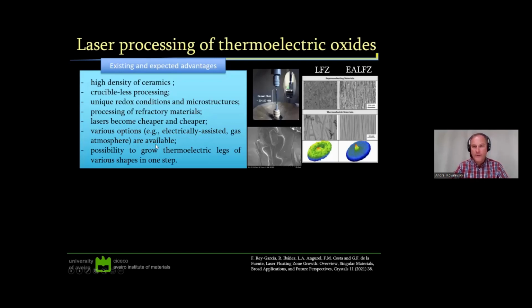And one more thing which actually doesn't work very well yet, but probably we can advance this point as well: the possibility to grow thermoelectric legs in various shapes just in one step. So we know the shape we need for a module, and we can grow it immediately by laser - this shape, this length, this thermoelectric leg.